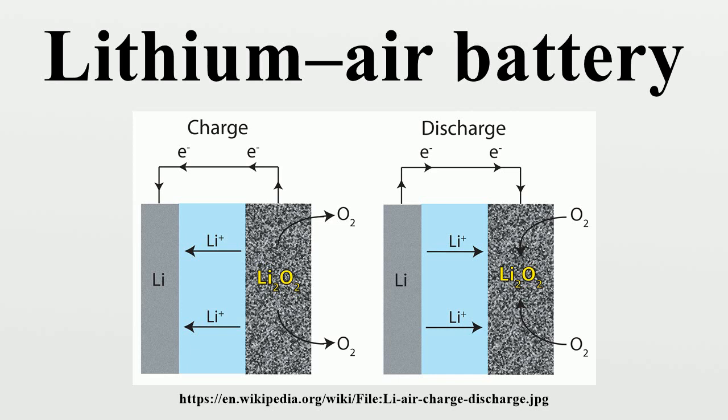Electrochemical. In current cell designs, the charge overpotential is much higher than the discharge overpotential. Significant charge overpotential indicates the presence of secondary reactions. As a result, electrical efficiency is only around 65%. Catalysts such as MnO2, Co, Pt and Au can potentially reduce the overpotentials, but the effect is poorly understood. Several catalysts improve cathode performance, notably MnO2. The mechanism of improvement is unknown, but may alter the structure of the oxide deposits.